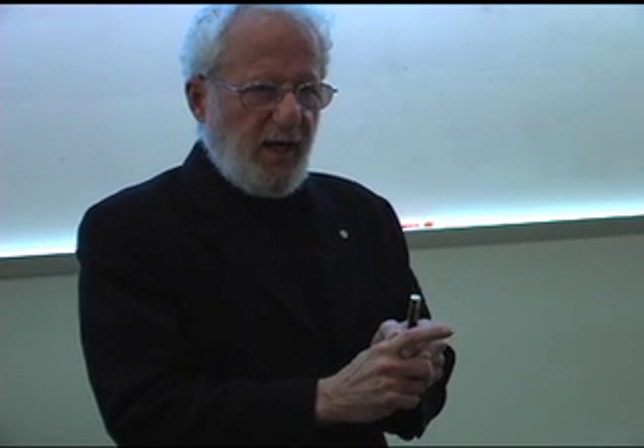Now, this is looking top down on the cell. What I really like to do is cut a cross section. So I'll use a focused ion beam to cut a cross section, and another one, and I'll take that thin cross section, and you can believe me that I've never done this, but I have some students who have, and who have very good hands. And you can take those very thin sections, they're going to be 60 nanometers in thickness, and you can put them on an electron microscope grid, and you can image them. And here, for example, is what you see.